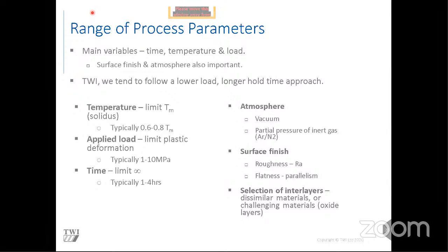So when we're diffusion bonding, there are two sets of parameters, really. There's the furnace parameters, which are the time at which you hold, the temperature you go to, and the amount of pressure you apply. So I've put load there. It's actually incorrect. It's pressure, but load is a function of pressure. And the other two parameters are the surface finish of the components and the atmosphere in which you diffusion bond. So at TWI, we have a general approach where we use a lower load or lower pressure and a longer hold time.